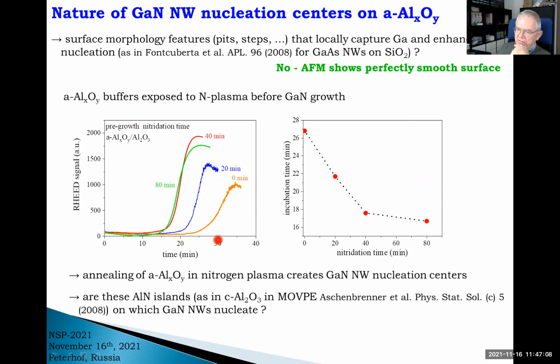This means that there must be a kind of reaction of aluminum oxide with the nitrogen plasma that leads to the creation of some centers, which later on act as nucleation centers for gallium nitride. And this is actually a very well-known phenomenon, because in MOVPE of gallium nitride, it's well known that it's useful to expose the sapphire substrate to ammonia flow at high temperature, because then aluminum nitride regions are created that make nucleation of gallium nitride easier. So the question is whether this is really the case in our situation.